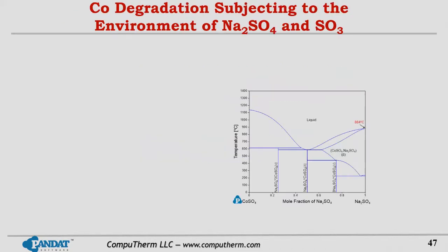For example, this diagram shows cobalt sulfate with sodium sulfate, this pseudo-binary system. As you can see, the melting temperature for pure sodium sulfate is 884 degrees C. When it forms a solid solution with cobalt sulfate, the melting temperature follows this purple line, and as you can see, it decreases to like 600 degrees C.